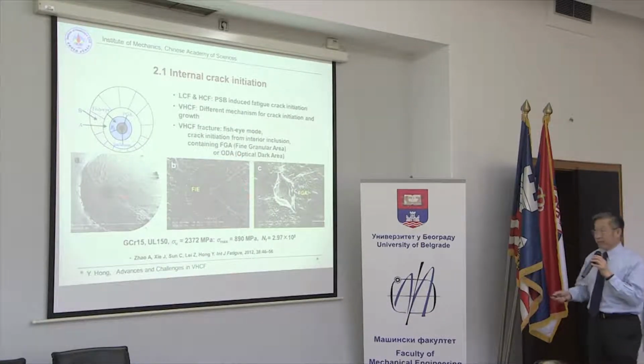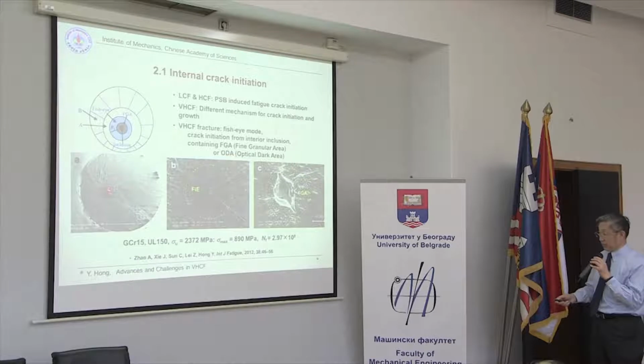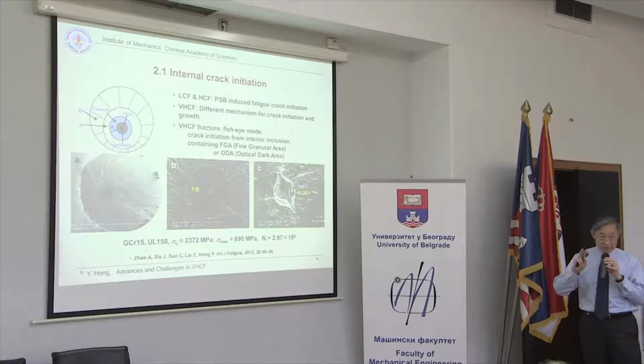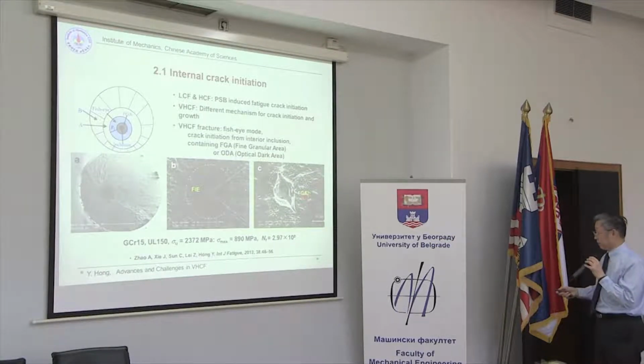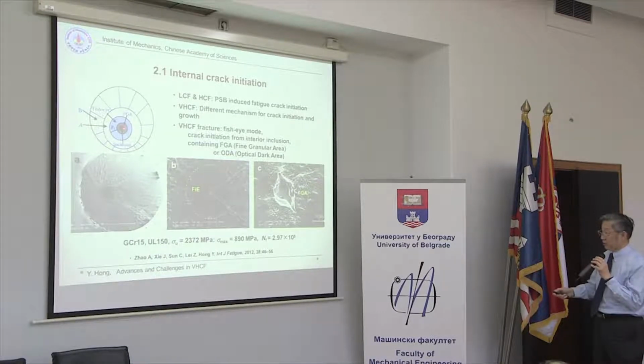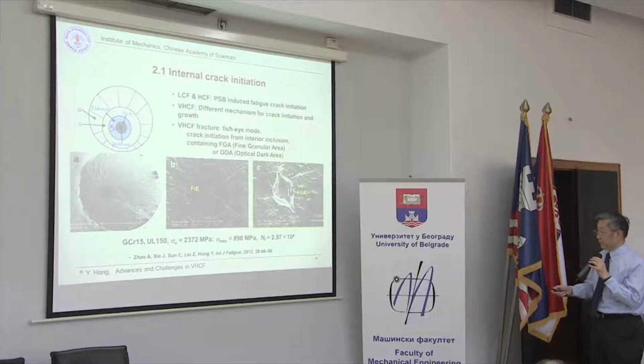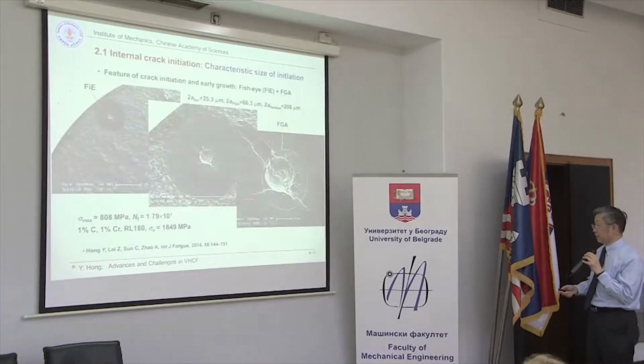And this is an example of very high cycle fatigue. We may see the initiation spot, and there's a morphology called fisheye, and around the initiation spot there's a rough fracture surface called fine granular area. And this is the schematic to show this morphology: initiation spot, FGA (fine granular area), and fisheye, and then crack growth region. And this is the case for very high cycle fatigue.